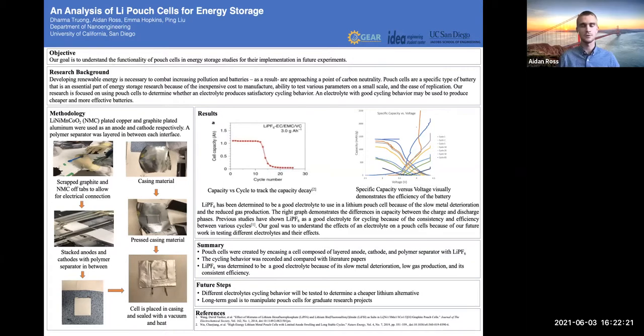Yeah, so our results, we used lithium hexafluorophosphate as our electrolyte, and in previous studies, it has been determined to be a good electrolyte to use in lithium pouch cells because of the slow metal deterioration and the reduced gas production. Now, as Dharma was talking about earlier, you don't want gas production in a battery because that's going to reduce the contact between the anode and cathode, which is then going to reduce the cell capacity.